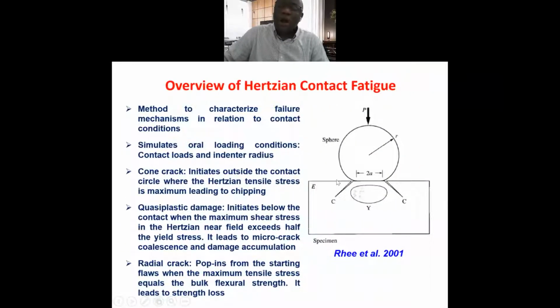Now, intraoral activities can be simulated by using Hertzian contact fatigue. Whenever a dental restoration is made, there is a need to understand the fatigue life and fatigue limit. This can also be simulated using Hertzian contact fatigue. It is better for characterizing failure mechanisms in relation to contact conditions. It simulates oral loading conditions, contact load and indenter radius. The contact load represents the biting force, while the indenter radius represents the cusp path.